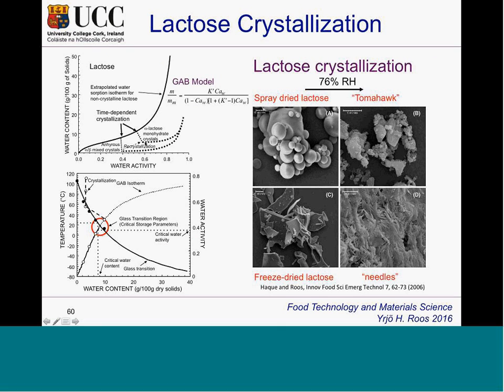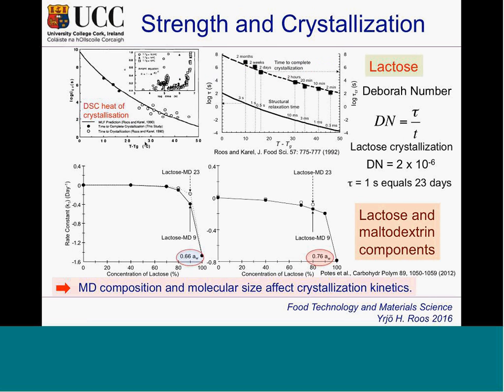Also, what we want to show is that if we look at crystalline behavior, we have some old data from myself that we published with Professor Karel on time to crystallization and the glass transition. They are very parallel to each other. That means that they have a difference in relaxation time. This is measured by DMA, and this is practically the Deborah number that is describing the relationship, which is very well established for this type of relaxation time versus time to crystallization. That indicates the importance of understanding relaxations above the glass transition.